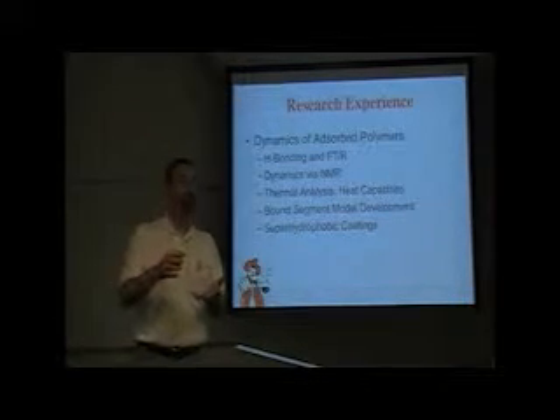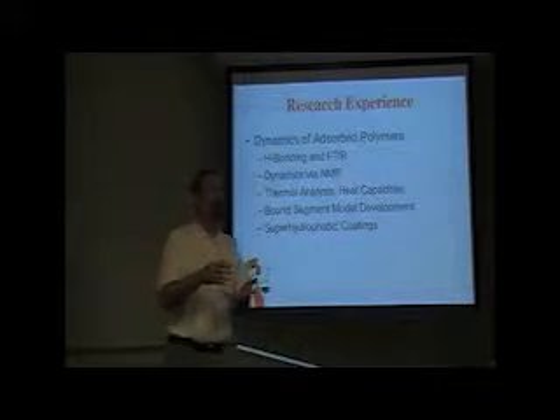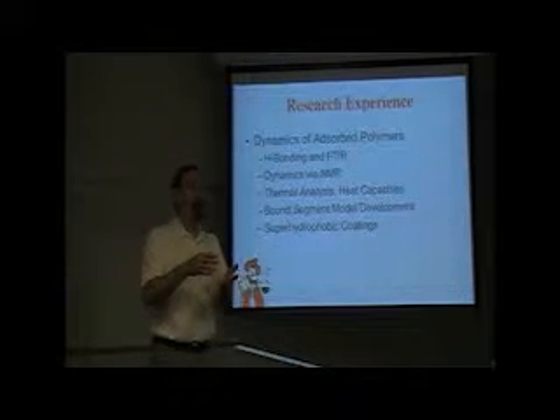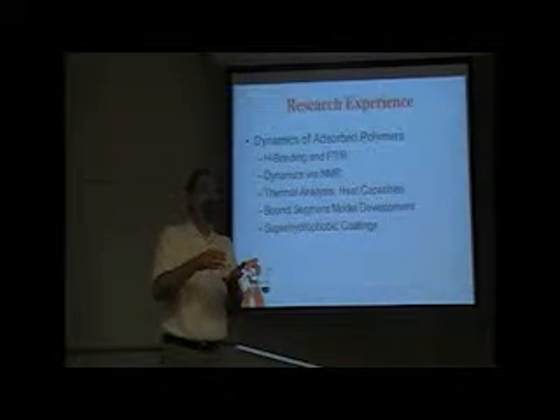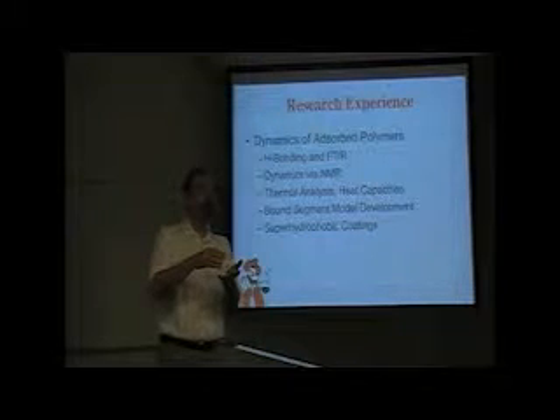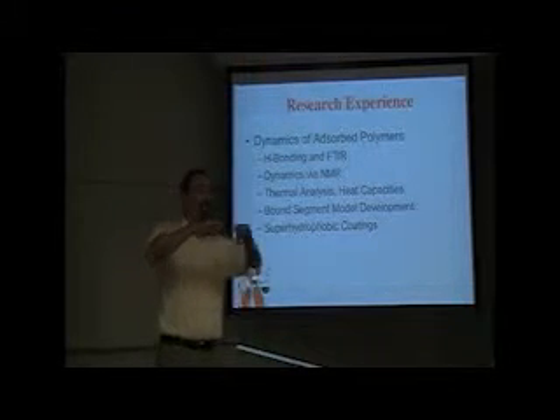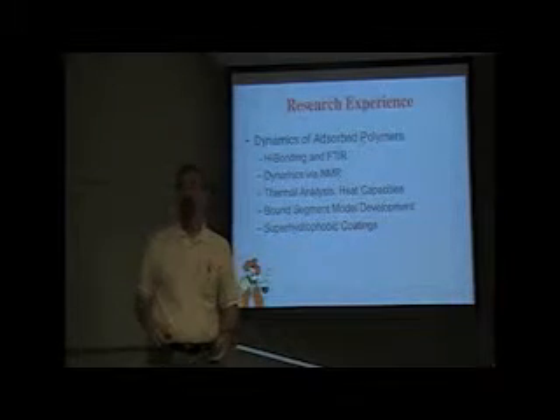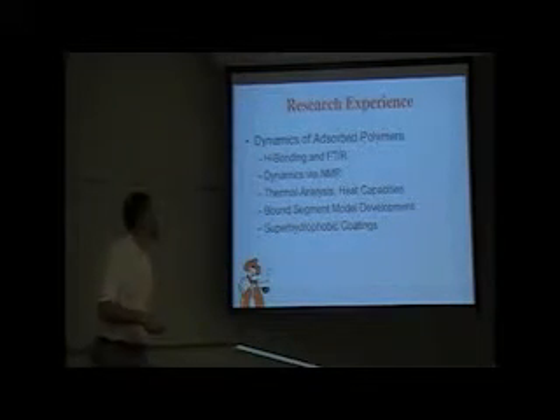By the way, if your surface polymer behaves differently than the bulk polymer, and you've got a chip in there, when the chip gets hot, if the polymer gets rubbery at a temperature that's lower than the bulk material, it expands, breaks this teeny tiny little wire, and you have a failure of your integrated circuit. So it's really kind of important.